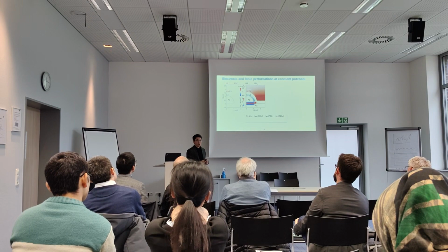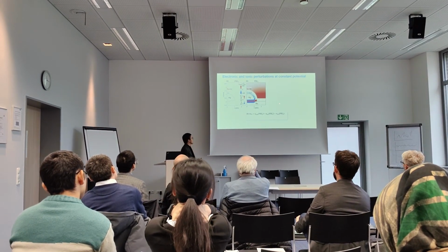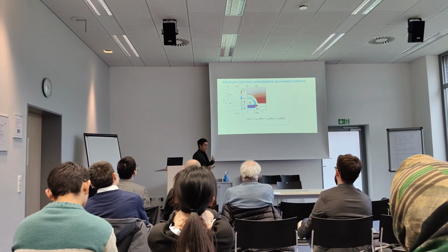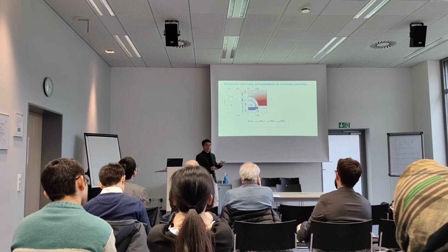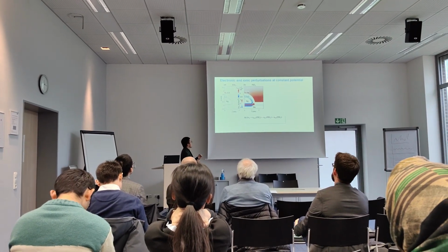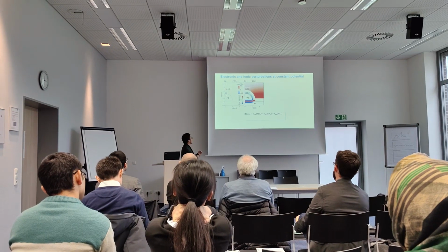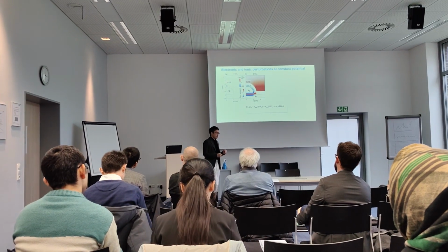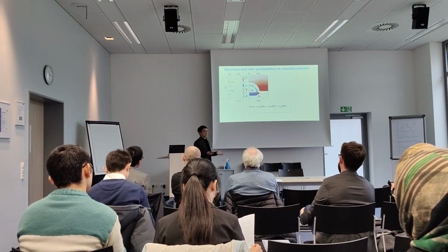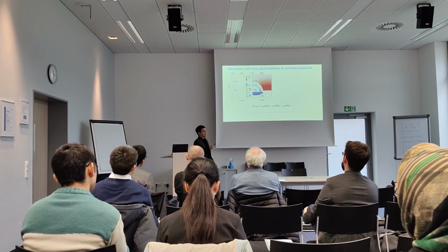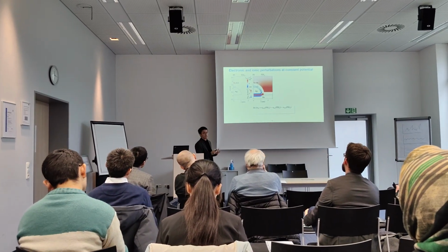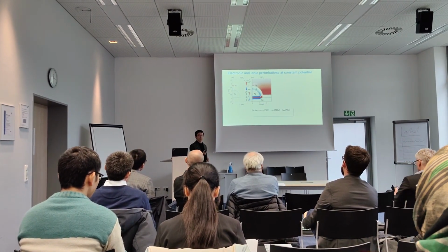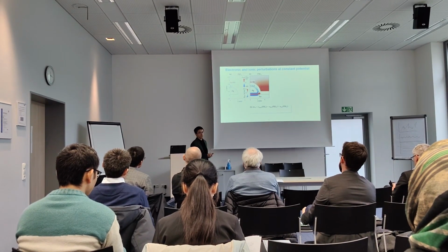You can see that the electronic and ionic properties are perturbed by this substrate despite being at the same potential. The next question is, how can we tune the electric potential to recover the previous ionic state and the previous electronic state? Why is it important? Because in electrochemistry we control everything by electric potential. We change the potential so that we have a certain ion concentration at our reaction plane. And a 0.2 volt difference in the onset potential of oxygen reduction or hydrogen evolution is significant.